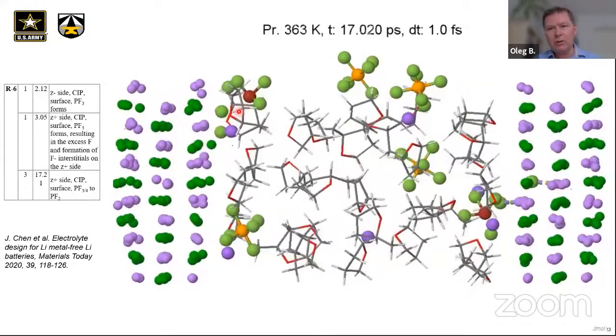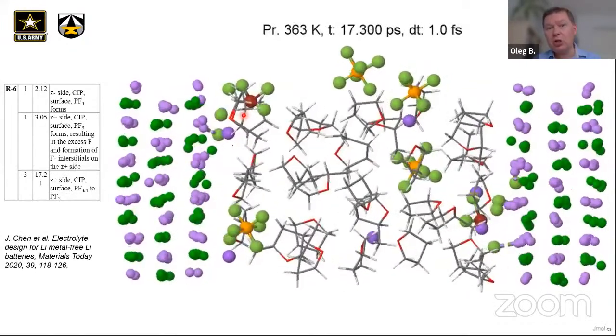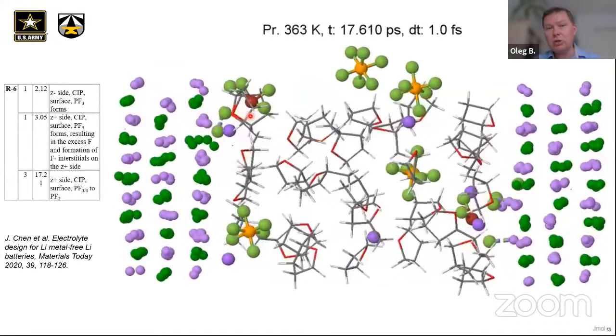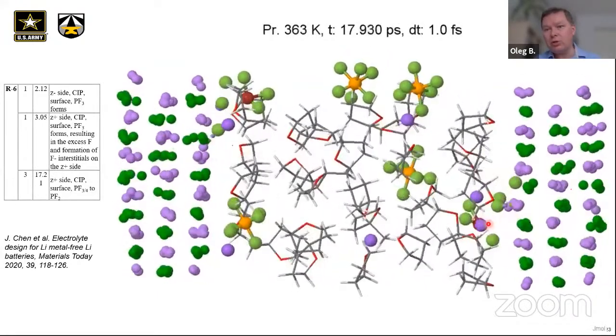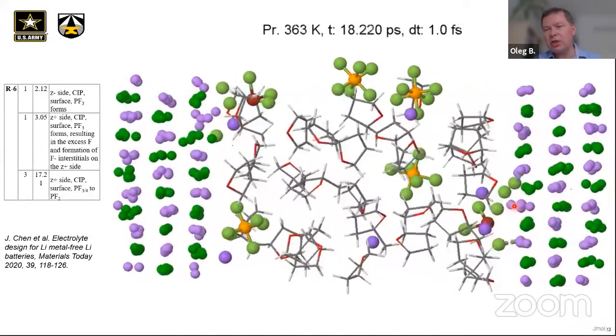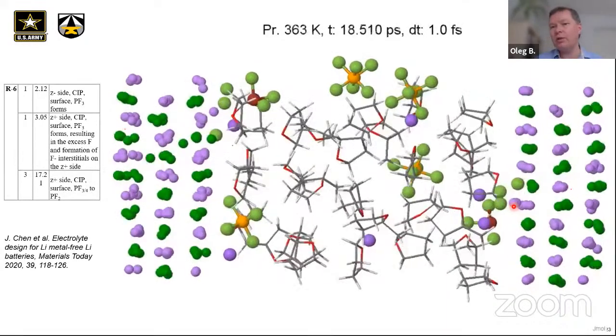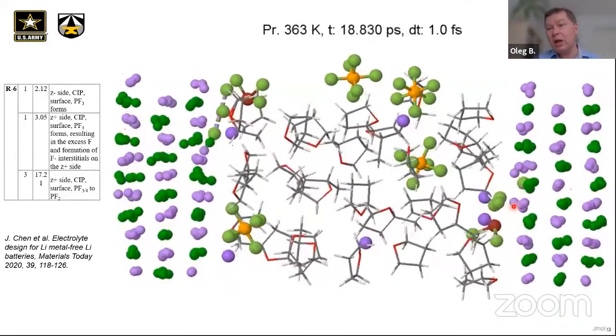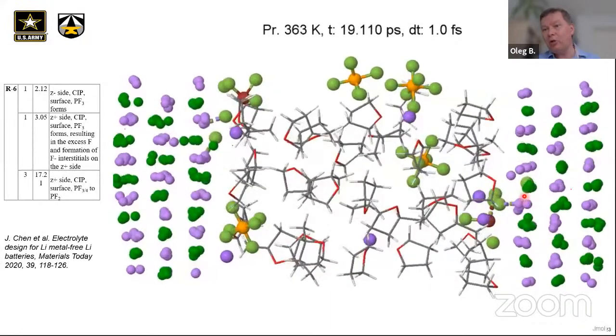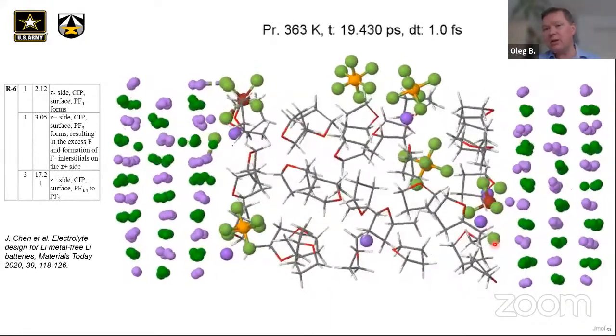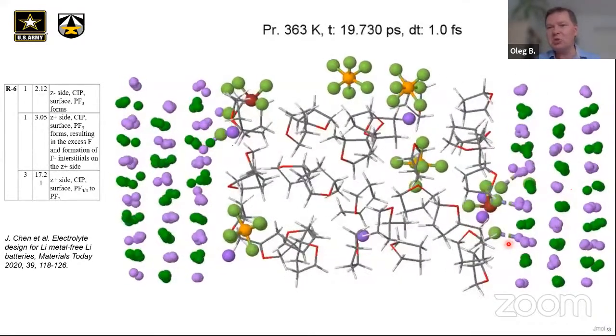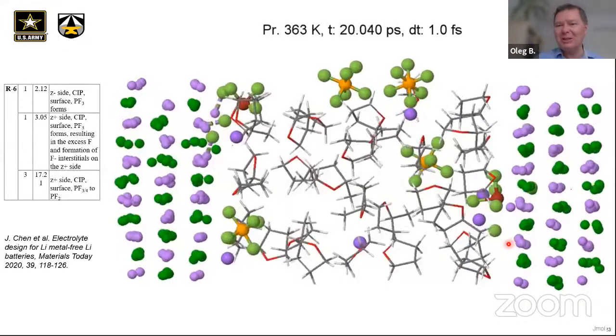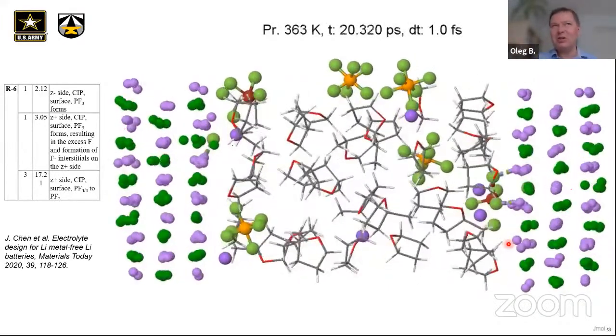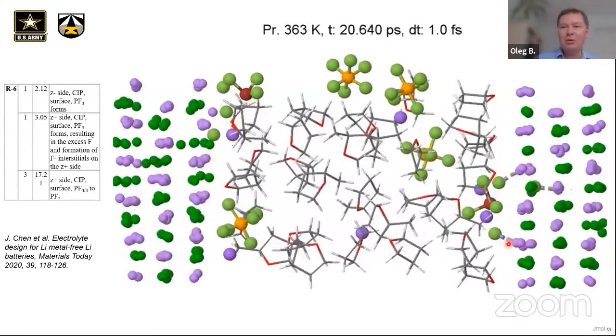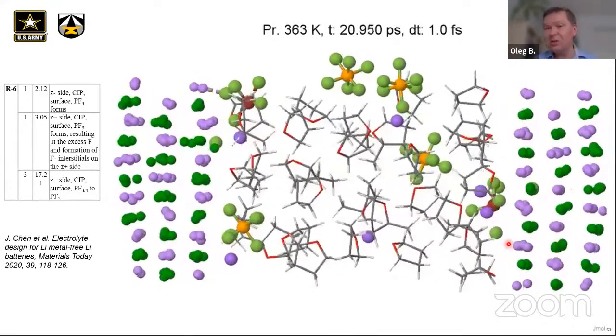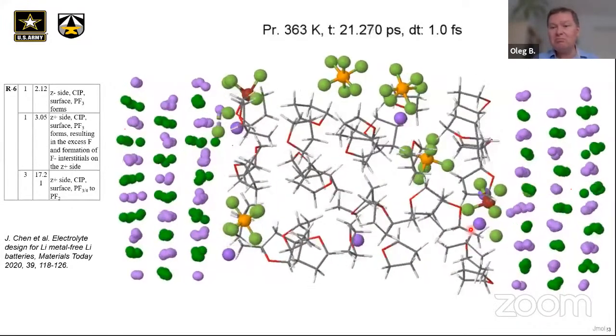What we saw is that those PF6 which were coordinated by 1 and 2 lithiums and also close to the surface, so fluorines would coordinate lithiums to the surface, were then preferential for undergoing reduction reactions on the surface. And there might be clues for local relaxation, as in a very thin layer, fluorine can also be kicked out due to these 3 fluorines being right next to it, right? So there is a large force to transfer fluorine or lithium out or fluorine in, right? And fluorine transfer seems to be one of the events which we observed.